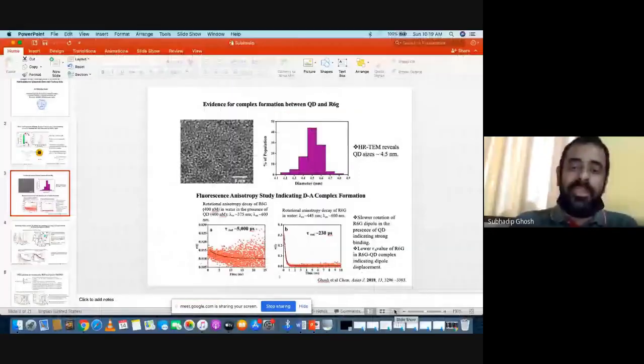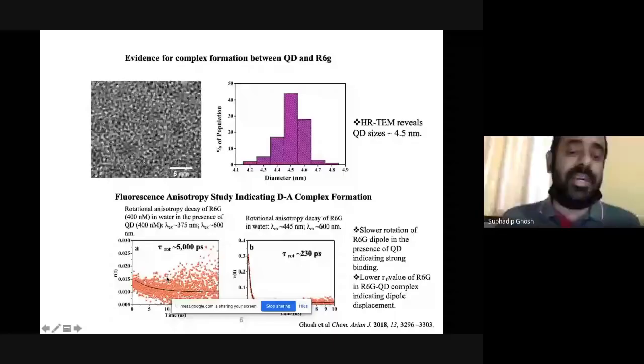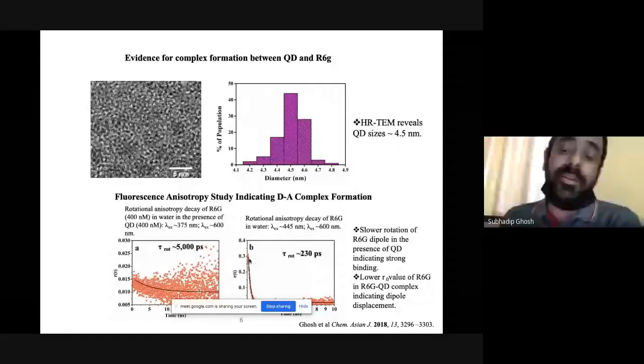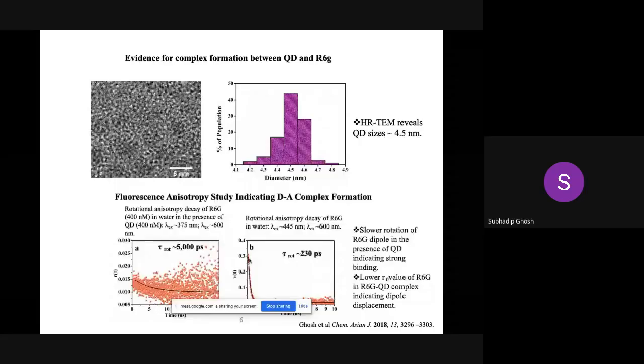Okay. So when rhodamine 6G forms a complex with the quantum dot, now the size is bulkier, so you can see the rotational anisotropy time gets longer. So this observation indicates that there is a complex formation between these two molecules, and this complex formation will lead to FRET. So this is showing the quenching of donor emission on addition of the quantum dot. We find the emission of the donor is decreasing